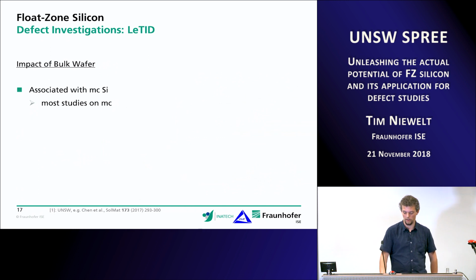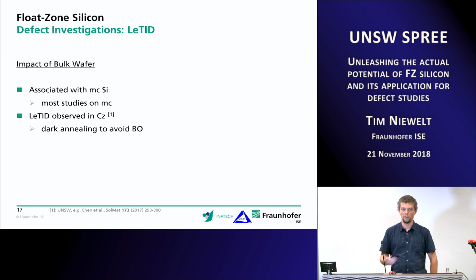The degradation has been associated with multicrystalline silicon mostly, and most studies in literature are using multicrystalline silicon because that's where the defect was found. However, UNSW, and I think mostly UNSW, has shown that the degradation, so LeTID, maybe I should spell it out, light and elevated temperature induced degradation, can also be observed in Czochralski grown silicon. Most of these experiments were done by dark annealing to create the defect, because otherwise the p-type Czochralski silicon would also show normal light induced degradation due to boron oxygen defects. But yeah, they have shown that it's the same.